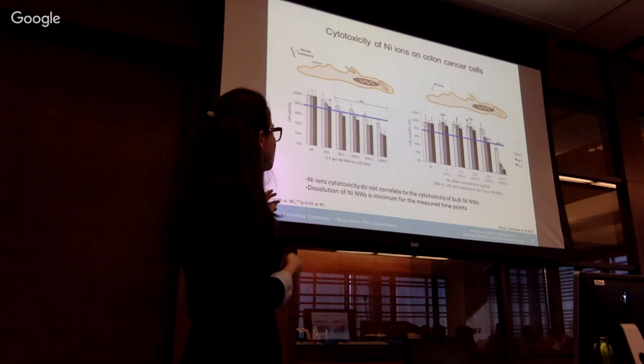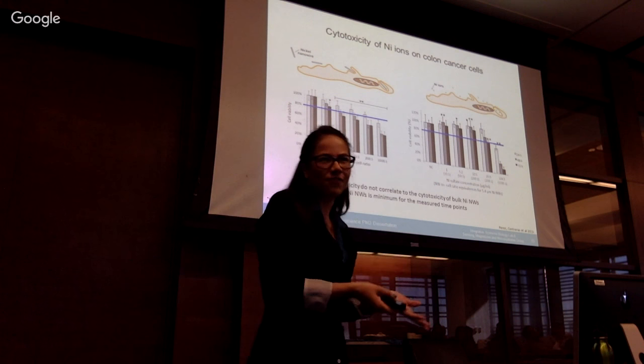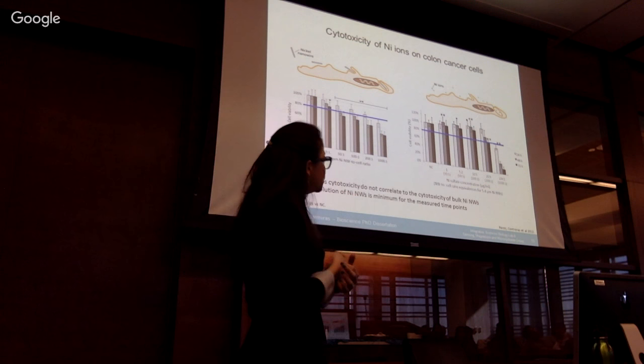If you compare the two profiles, for example, for concentrations below 200, they do not affect the cells at all. However, when you apply 1,000 concentration, they do, the nickel ions. What does this tell us? Well, first of all, that we don't see a correlation between the two. And secondly, that the dissolution of the wires is not significant in the process. If it were, you would have more nickel ions available, and then they would exert a similar toxicity behavior.